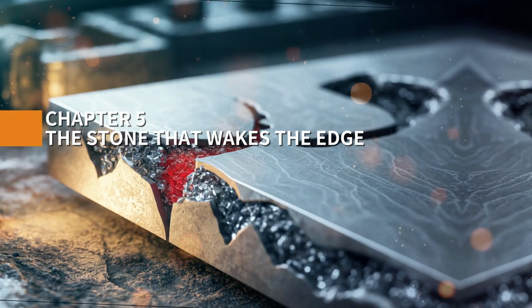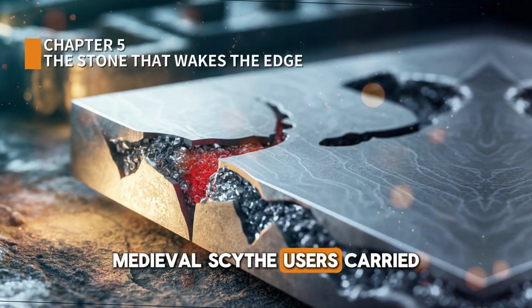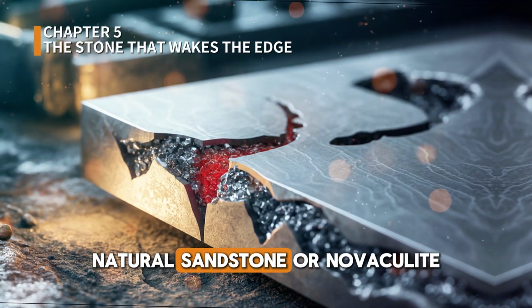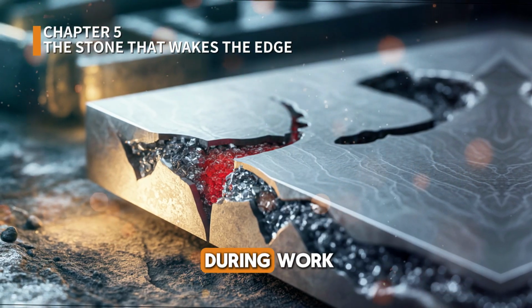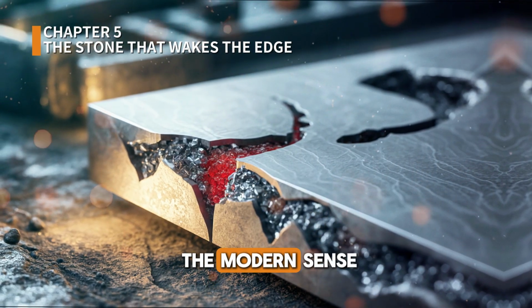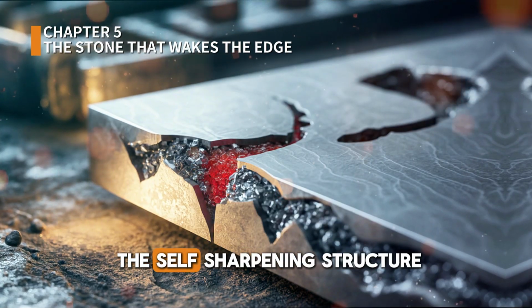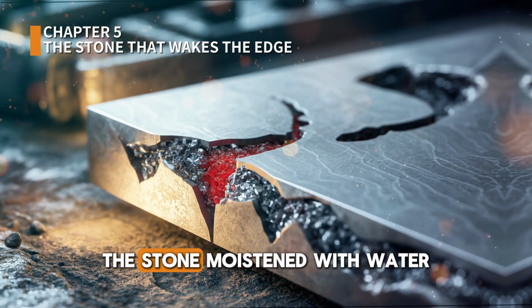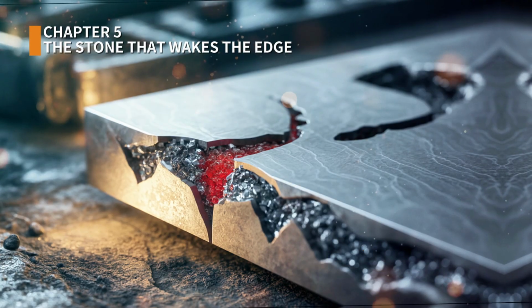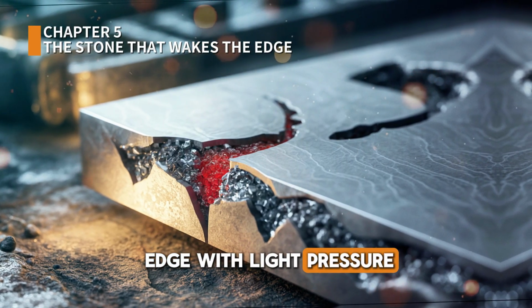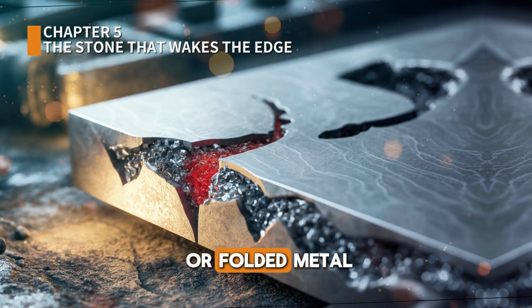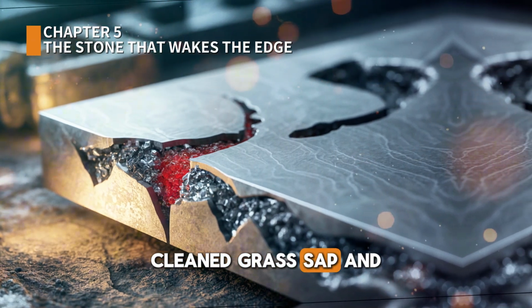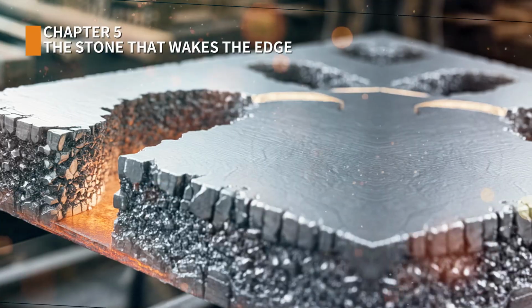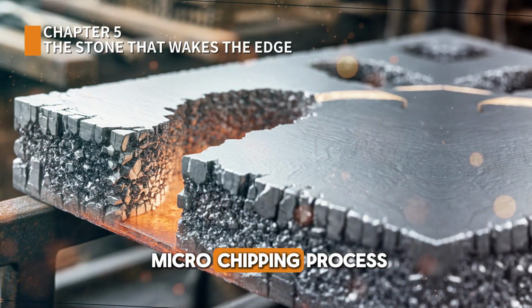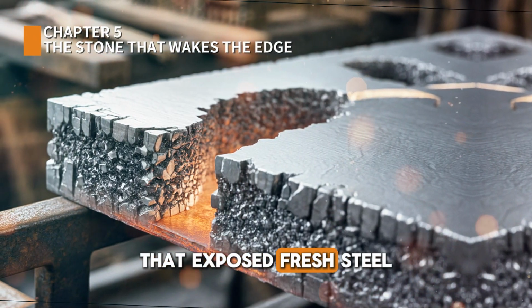Chapter 5. The stone that wakes the edge. Medieval scythe users carried whetstones, natural sandstone or novaculite, to hone the edge during work. This wasn't sharpening in the modern sense, but rather maintenance of the self-sharpening structure. The stone, moistened with water, was drawn along the edge with light pressure. This removed any burr or folded metal, cleaned grass, sap, and debris from the edge, and potentially triggered the microchipping process that exposed fresh steel.